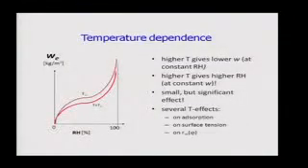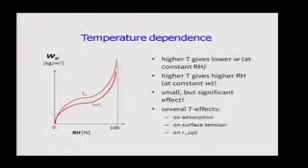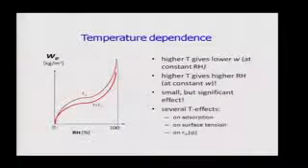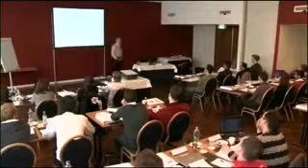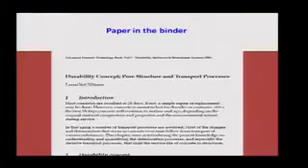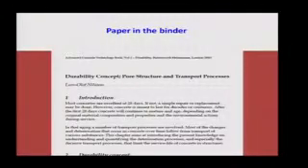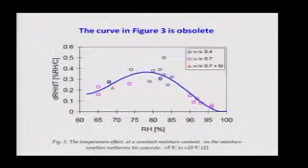The other example was referred to — the temperature dependence of the sorption isotherm. It's difficult to measure, almost impossible to measure directly as a sorption isotherm. So what we do is measure the horizontal distance between the two curves — the RH difference — instead of trying to measure the difference in moisture content, because that is very difficult to measure precisely. But it's much easier to measure the RH difference precisely. We did that, and in this paper in your binder, figure three is shown — and today we know that this curve is not correct.